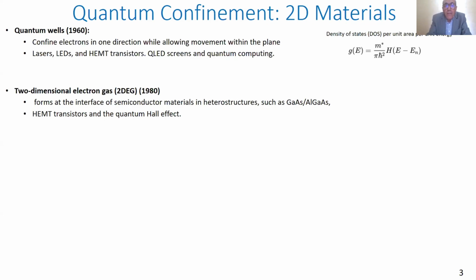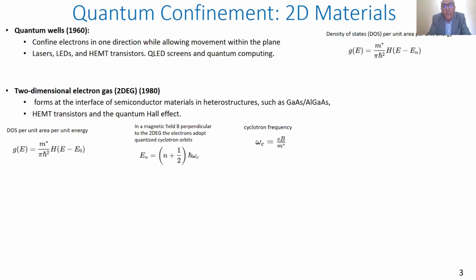In this case, there is confinement at the interface inside a heterostructure. For example, two semiconductors, gallium arsenide and aluminum gallium arsenide. The interface between these two semiconductors exhibits a two-dimensional confinement. There are many applications for that: high electron mobility transistor and quantum Hall effect. And in a magnetic field perpendicular to this 2D electron gas, the electrons adopt quantized cyclotron orbits with Landau levels and also with cyclotron frequency.